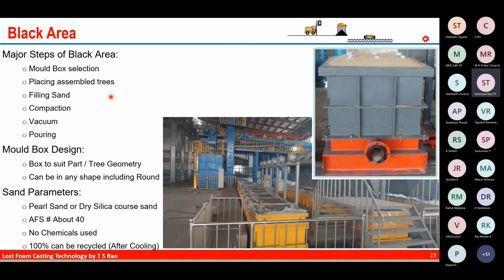The mold box design should suit the part geometry or the tree geometry. And boxes can be any shape. Even I have seen round circular mold boxes as well. And sand parameters, it can be a normal dry silica sand, or we can use pearl sand or any sand which granules about AFS number 40. No chemicals required to be added in the sand. 100% of the sand can be recycled after cooling and removing the fines.